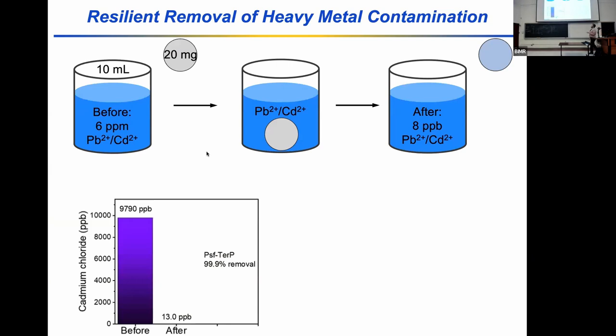But I think the most exciting result in my perspective is captured in this slide right here, where let's think about some more hazardous heavy metal ions. And so we'll talk about 6 parts per million lead or cadmium contamination. And we'll take 10 milliliters of this solution, plop a little bit of our membrane in there, shake it around for a short period of time like we did in the prior video, extract the membrane, and then measure the concentration of metal ion contaminants using ICP-OES in that retained solution.